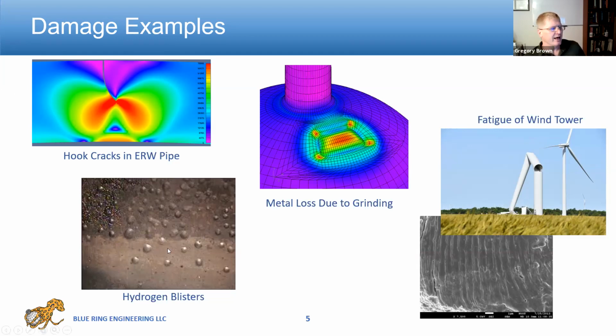Picture in the lower left, this is an example of hydrogen damage. If you ever have a carbon or low alloy steel and you have the presence of hydrogen, you can get hydrogen damage. Blistering is one type of hydrogen damage. You can also have what's called hydrogen-induced cracking, or also you can have stress-oriented hydrogen cracking. A lot of different types of damage due to that presence of hydrogen. 579 is going to give you guidelines on how to assess those.